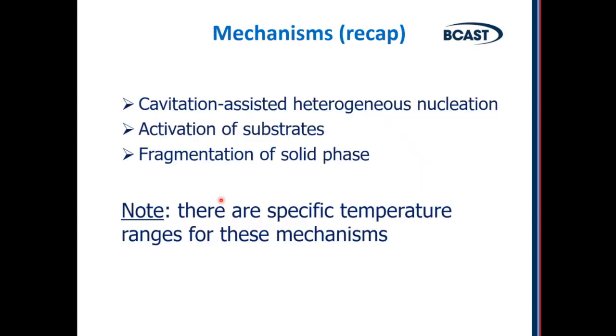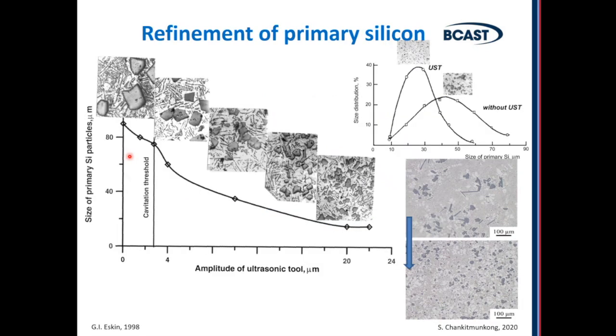So the mechanisms are cavitation-assisted heterogeneous nucleation through activation of substrates, and also fragmentation of solid phase. But note that there are specific temperature ranges for these mechanisms. So for that, you need to treat above the liquidus. For this, you need to treat below the liquidus. So you can achieve the refinement of primary phases, primary intermetallics.